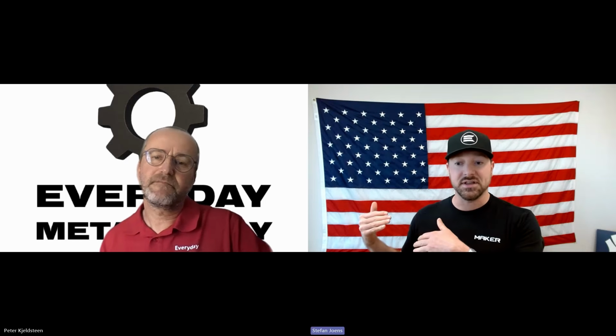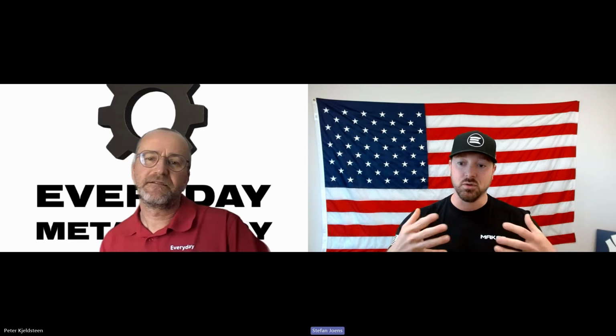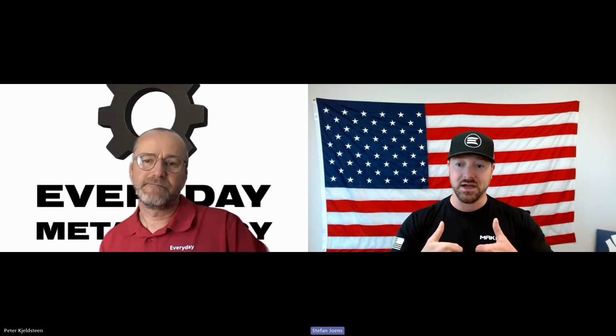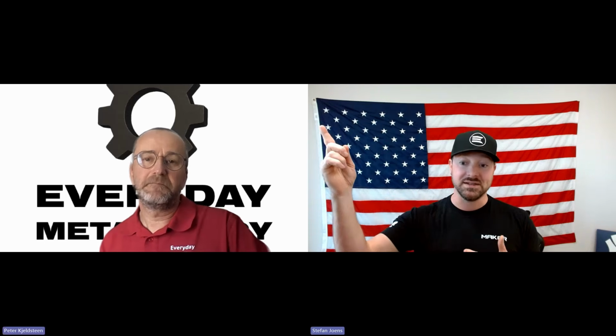You want, if you can be titanium, it's great because it's an everything getter, right? The other side to it is traditional titanium processing in our industry has always, if you look back in the ages and the archives, it's always done in high vacuum, right? Because we want no oxygen around the product. The problem in today's world, when you look at furnace technology, is it's a box in a box with a high vacuum system on the outside. And we're looking at gas flow from a molecular perspective where it's no direct line predictability, right? It bounces around in whatever kind of nonsense it wants to do. So any oxygen molecule in that area still is generally going to find your product or the getter before it finds the vacuum exhaust.